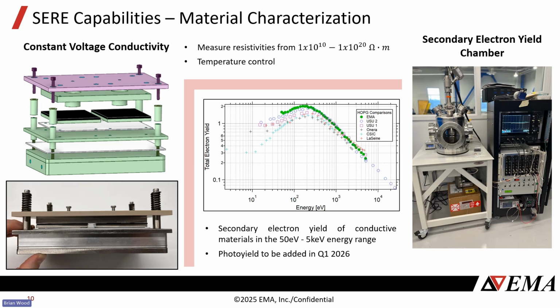Also the constant voltage conductivity, so basically how conductive something is. We haven't quite got this system going yet, but we've made the fixture for it. And that's essentially pretty straightforward. You're just sandwiching the material, applying a voltage to it, and measuring the current across it. Based off of the geometry of the sample, you can just calculate the conductivity or the resistivity.